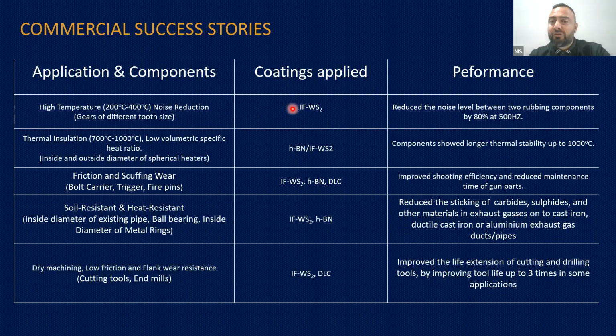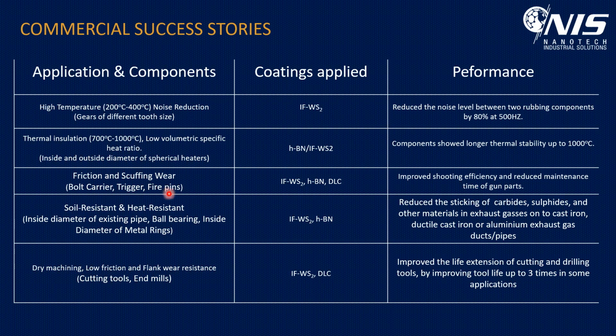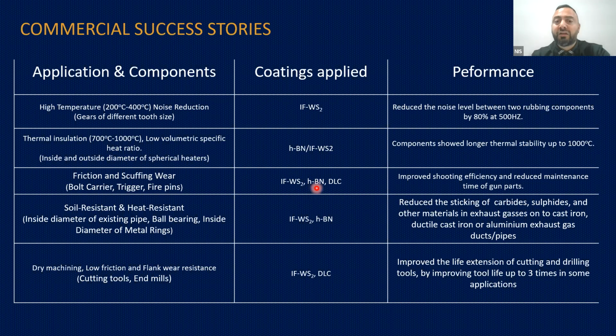So here are several applications where it's already used: high temperature noise reduction for different gears and tooth size, thermal insulation up to 700 degrees C to 1000 degrees C for low volumetric specific heat ratio. It could be spherical heaters, friction, scuffing, wear, like on bolt carriers, triggers, firing pins for defense applications, and it's IF-WS2 with hexagonal boron nitride and diamond-like carbon. It could be soil resistant and heat resistant applications, like the inside diameter of exhaust pipes, ball bearings, metal rings. Also dry machining, low friction and flank wear resistance with cutting tools and end mills, and many, many more. There are thousands or even hundreds of thousands of different applications.